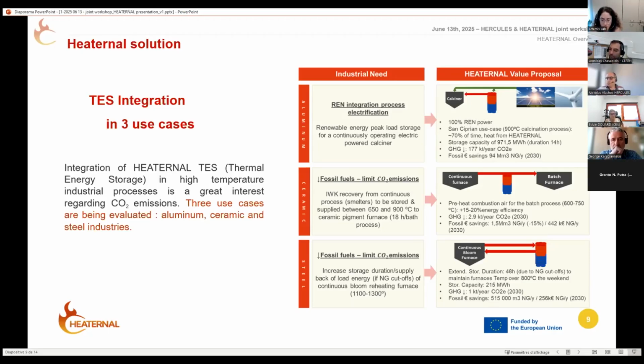And the stored heat will be used to preheat the air between 650 and 900 degrees. And the third use case is the steel industry, represented by Ugitech. And for this case, industrial waste heat will be stored to heat a steel furnace during a natural gas shortage or cutoff. And this storage will also be used to maintain the furnace temperature during the weekend when the process is not running. So we see that in all these cases, HEATERNAL storage will enable to reduce the use of natural gas.